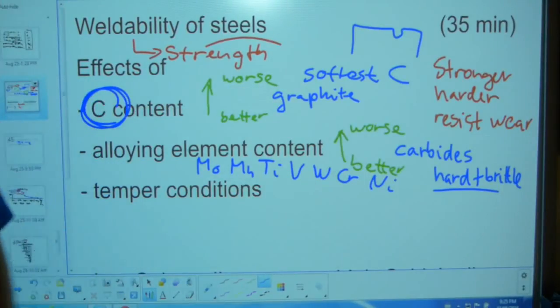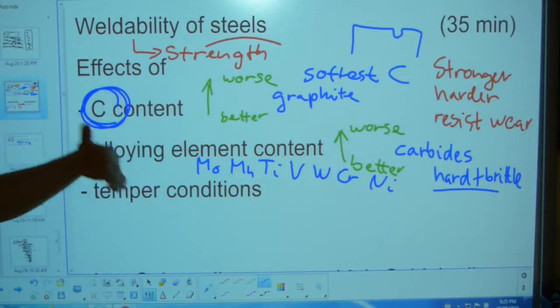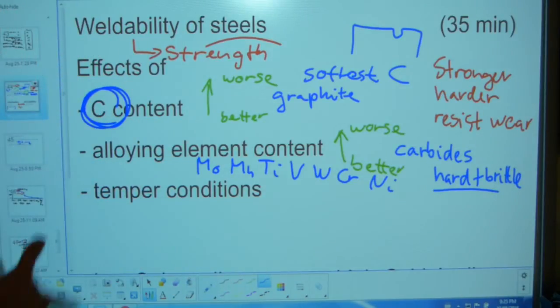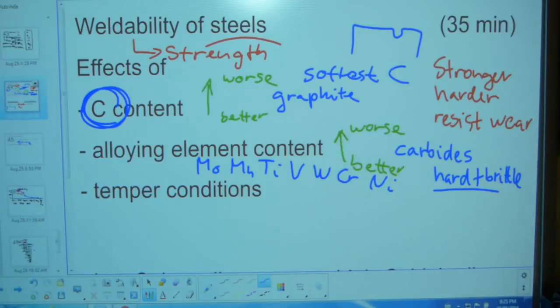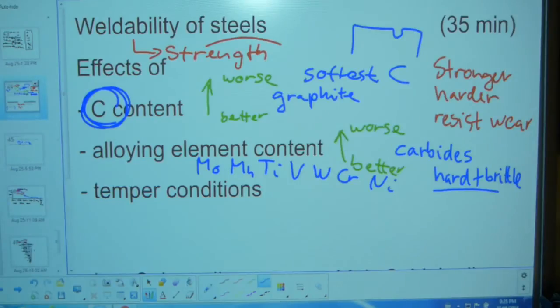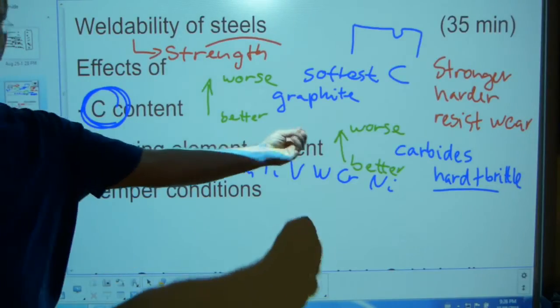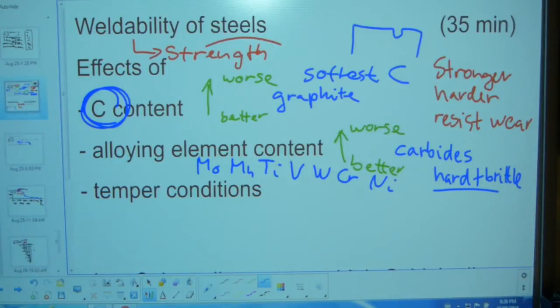These carbides are so hard and so brittle that they make weldability really bad. After being welded, these carbides need to be softened. They do dissolve with heat treatment, namely tempering or normalizing or spheroidizing or process annealing or one of these metallurgical processes. Okay, so that's how carbides can dissolve back into the matrix instead of clumping together and making the tools brittle and pretty much useless for practical purposes.